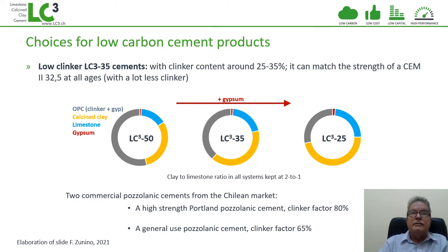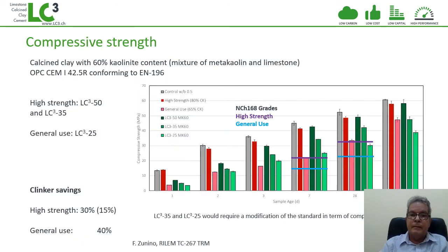I mean, you don't need a very high strength cement, and we have to see what happens if we continue to replace more clinker with a combination of calcined clay and limestone. And this is really what happens here. You see here, this is a study that was carried out at EPFL by Franco Sunino, presented recently at the technical committee Rilem. And you see here that even from the very early ages, we're dealing with cements that have clinker content between 25 and 35%. And at 7 days and 28 days, we're complying with the strength requirements of these materials. I mean, we're outperforming these standards with these materials.